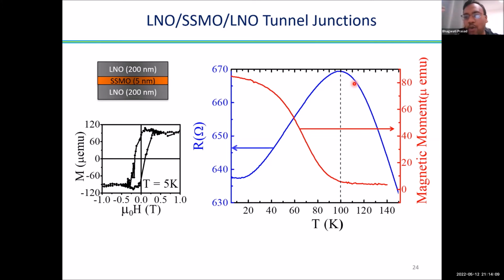That's why people could publish millions of papers in manganite systems, because when you change a little bit here and there, things change dramatically. Yeah, but what I had seen is that the TC is quite sensitive, but the scaling behavior not necessarily. But typically, when you take the film and do nanofabrication on things, typically the order temperature would go rather down than up. But to have a consistent explanation here, you would need the order temperature to go up with the nanofabrication. Am I right? A little bit up. I mean, that can happen, but it's not changing drastically also. Yeah.